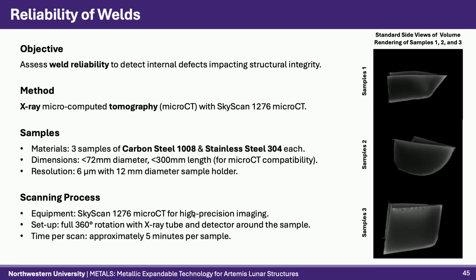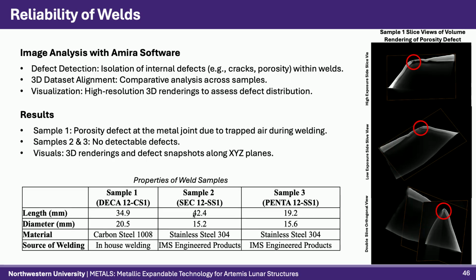We generated high-resolution images which were compiled into 3D renderings, which can be seen here, and were analyzed using the Amira software from Thermo Fisher Scientific to identify defects like cracks and porosities in the welds. Our analysis revealed that sample 1 exhibited a porosity defect at the joint, which is just air bubbles trapped in the welds, and it can be visualized in these red circled areas.